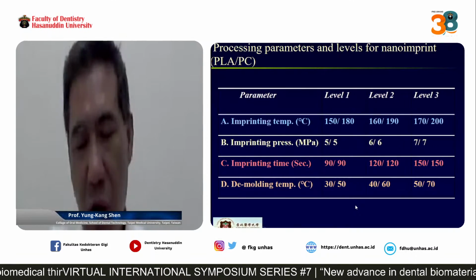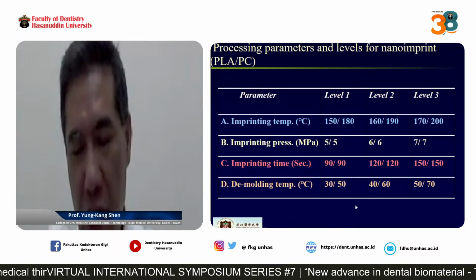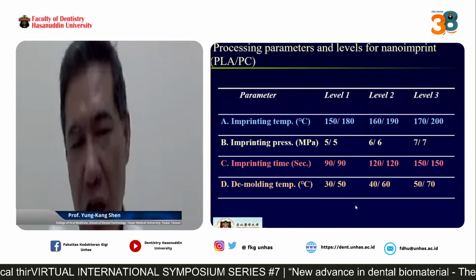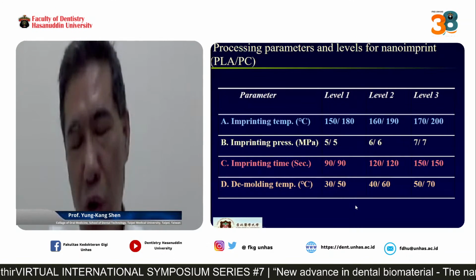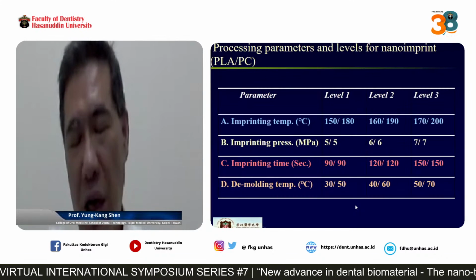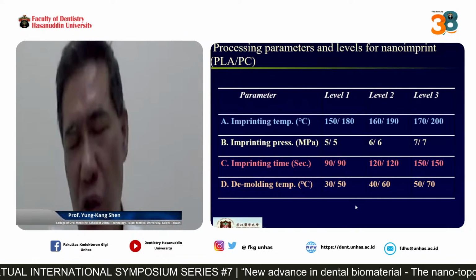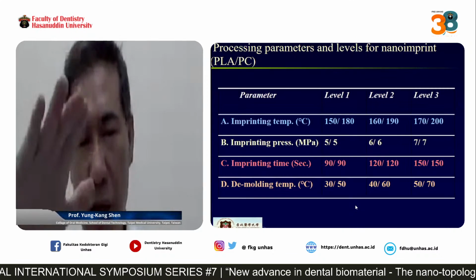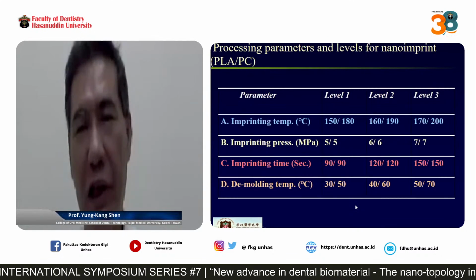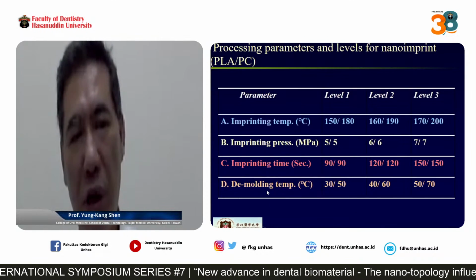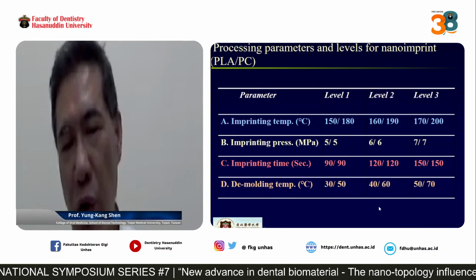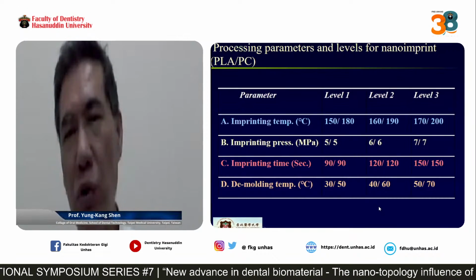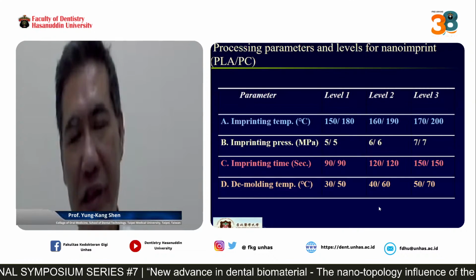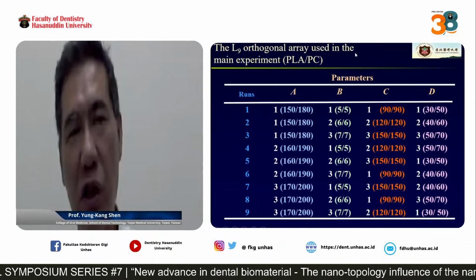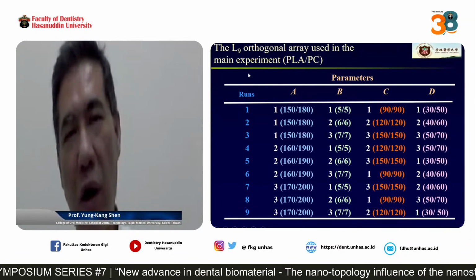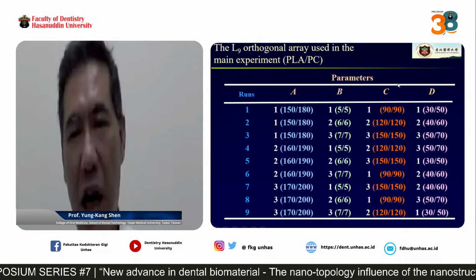Demolding temperature is when we imprint the AAO on the polymer thin film, and the temperature will cool down to the polymer glass transition temperature, and then we can do the demolding. So the demolding temperature is shown on here. Because there are 4 parameters and 3 levels in our research, we use the Taguchi method to get the optimal processing on here. And you can see this is the Taguchi method. We use the L9 method on here.